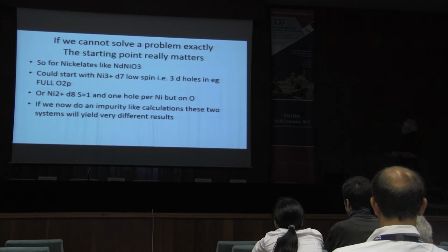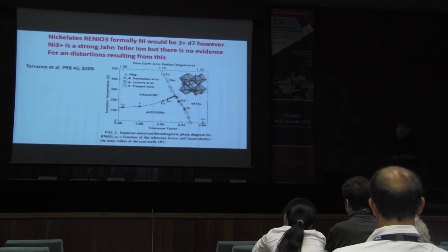Now, I said already, if we cannot solve a problem exactly, the starting point really matters, and I've gone through all of this. Rather than having nickel 3+, I would take nickel 2+, would be D8 with a spin of 1, and 1 hole per nickel would be in an oxygen 2p band.